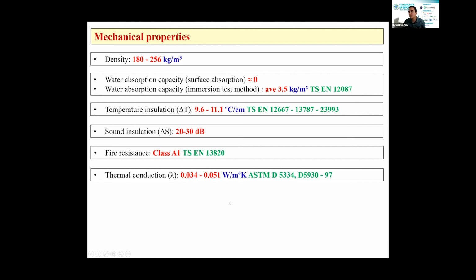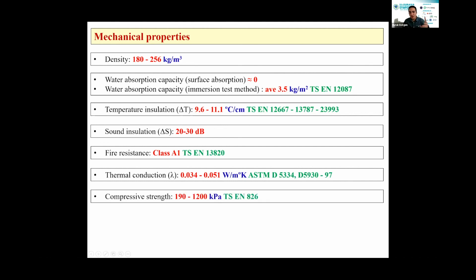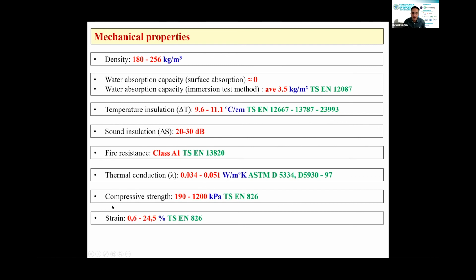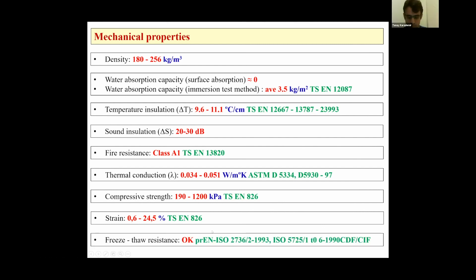with the unit of watt per meter Kelvin. And the compressive strength is maybe the unique point of our material. The compressive strength value can be reached up to 1.2 megapascal. It is also an incredible value because it is an insulation material. If you compare it with XPS, EPS, or rock wool, glass wool, any type of insulation material, it is so high level, and its strain can be reached up to around 25% under this amount of compressive strength. So some of our materials are brittle, some of our materials can be classified as ductile elements. And freeze-thaw resistance is okay. There is no problem with the freeze-thaw effect.